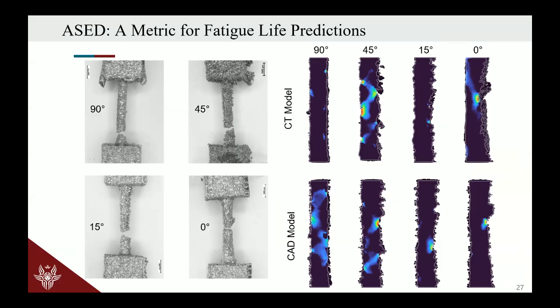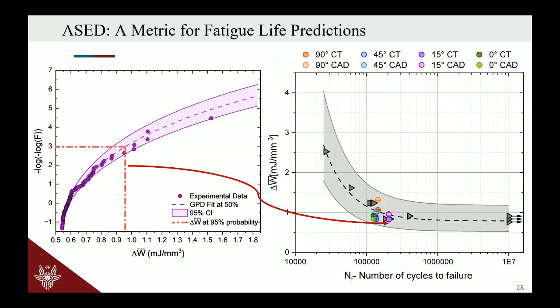It works not very well only for the 90 degrees sample because the orientation is very extreme and we are still improving the model, but for the 45, 15 and 0, it is predicting quite perfectly the initiation point of the crack. And after that, using the strain energy density, also here I will not go into much detail, we were able to summarize all the data from different orientation angles and from different geometries inside the same scatter band, providing a kind of master curve for lattice materials.